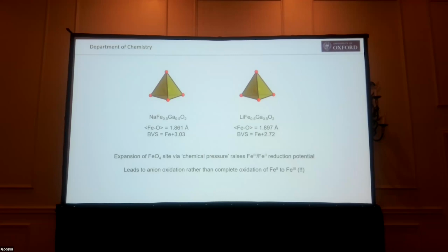However, after all this effort, you find that you thought making lithium-ion cathodes out of iron was hard, and you discover it's even harder than you thought. Because the irreversible oxygen redox is the real killer, unless you can find a way to switch that off, these iron-based cathode materials aren't really going to work.